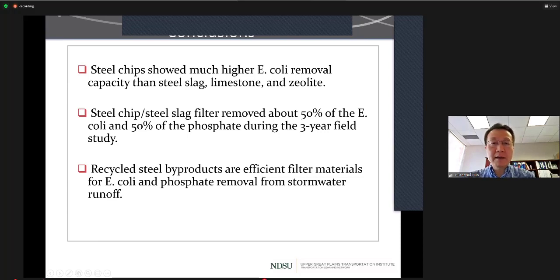So these are conclusions from our batch, column, and field scale study. First, steel chips showed much higher E. coli removal capacity than steel slag, limestone, and zeolite. Steel chips and steel slag filter removed about 50% of the E. coli and about 50% of the phosphate during the 3-year field study at City of Brookings. And overall, we conclude that recycled steel byproducts are efficient filter materials for E. coli and phosphate removal from stormwater runoff.